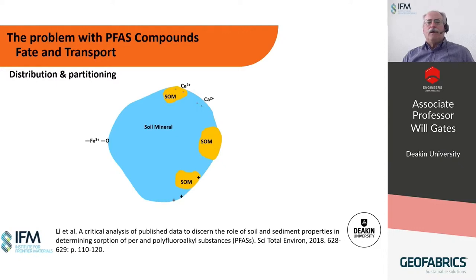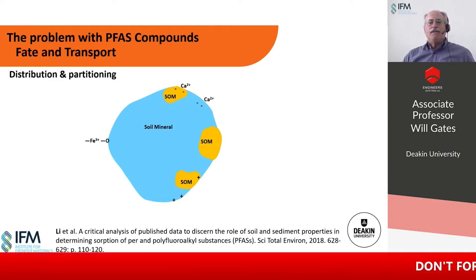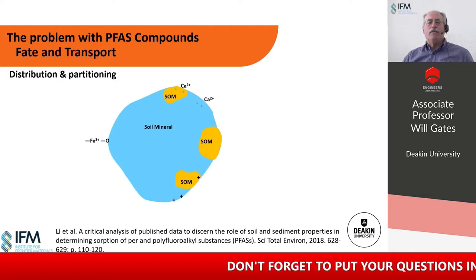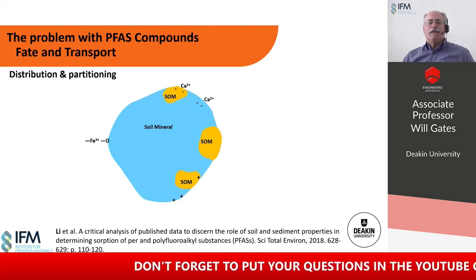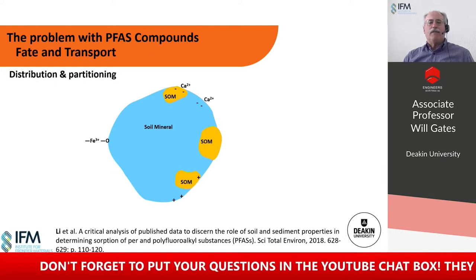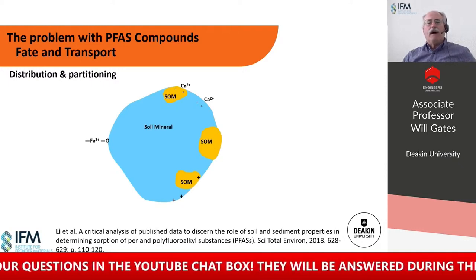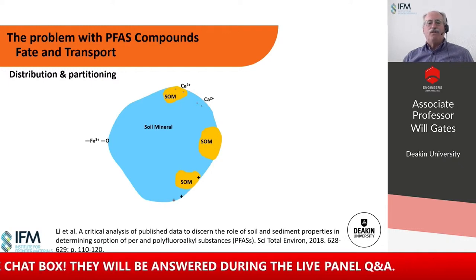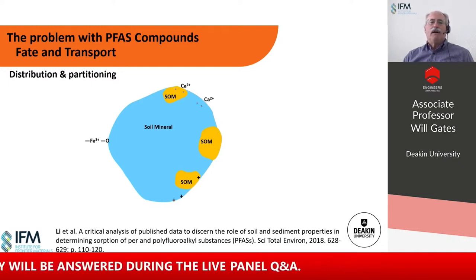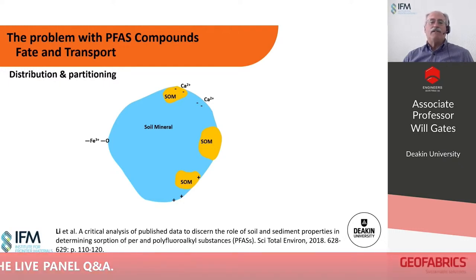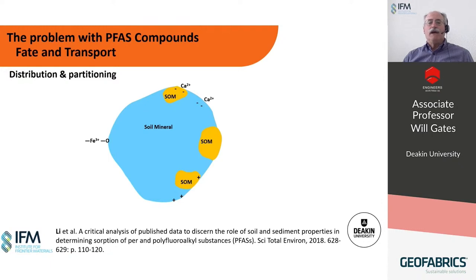Because organic carbon is present in many compacted clay liners in the form of natural soil humic materials, we can expect some interaction of the PFAS compounds with these. Soil organic carbon will have generally high cation and anion exchange capacities, a large pH range at which these variable charges can occur, and high surface areas and associated porosities that are all responsible for PFAS adsorption and retardation interactions in compacted clay liners.